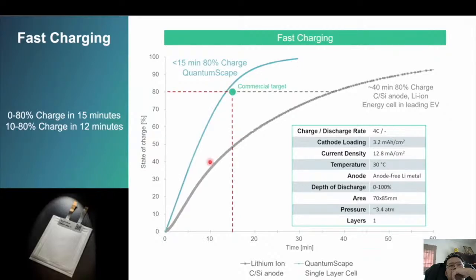What's shown in gray here is data that we didn't take in our lab, but that we found published on a leading automotive cell hooked up to a supercharger that in 15 minutes gets to about 50%. And then the charge rate really has to taper off after then to avoid this problem that I spoke of earlier of lithium plating. So to get to 80% takes about 40 minutes in these type of cells.